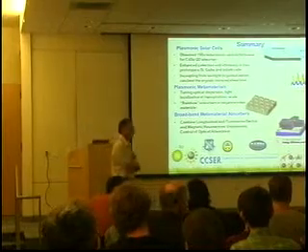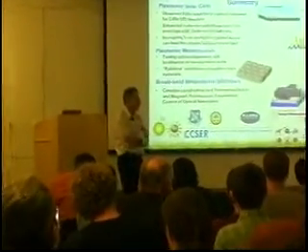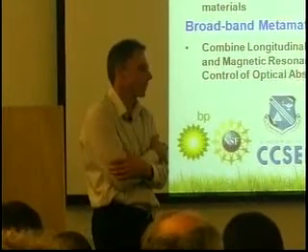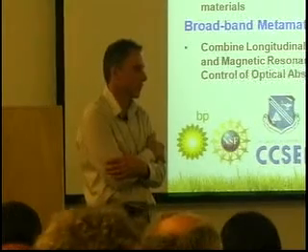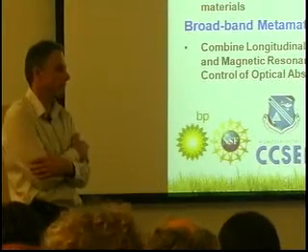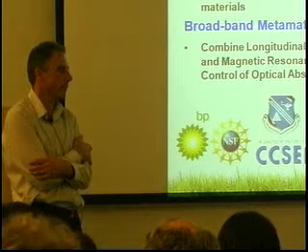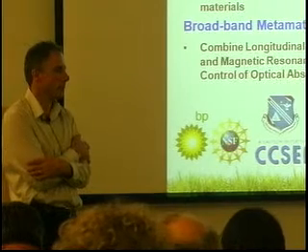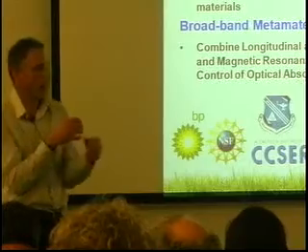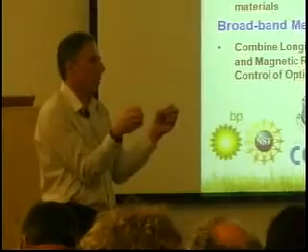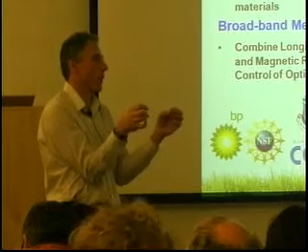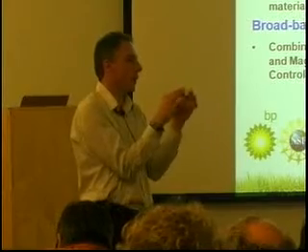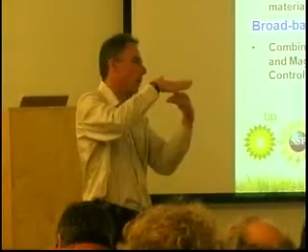In plasmonics, from what you said, I understand that you use a method to enhance absorption by coupling the incoming radiation into certain bandgap modes or charge density waves. Do these modes, the charge density itself, constitute photocarriers, or do they couple with the charge carriers in the material to generate them? Well, the polarization of the electrons in the metal, those are electrons that stay in the metal. What generates the photocarriers in the semiconductor is the confined EM field in the mode near the surface.